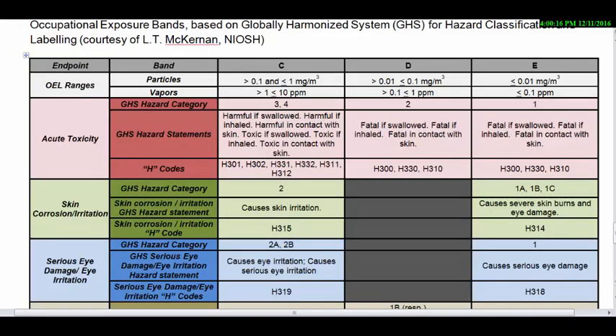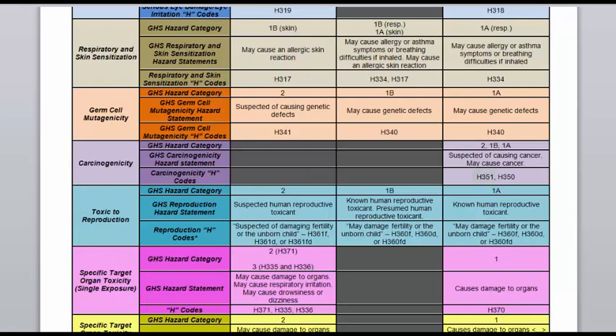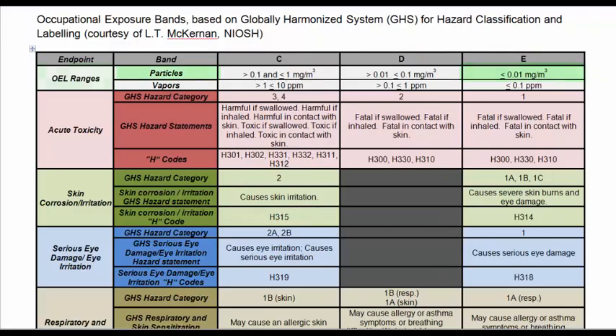Using the H codes, place silicon carbide nanopowder into an occupational exposure band using the NIOSH GHS-based occupational exposure band chart. Here, H315, H319, and H335 fall on band C. However, H351 falls on band E. Since band E is more protective than C, we place silicon carbide nanopowder in band E. Therefore, the occupational exposure limit or upper range of silicon carbide nanopowder particles is less than 0.01 mg per cubic meter.